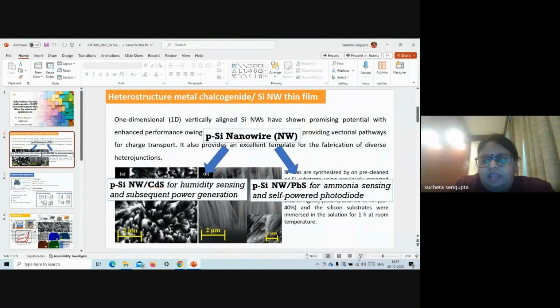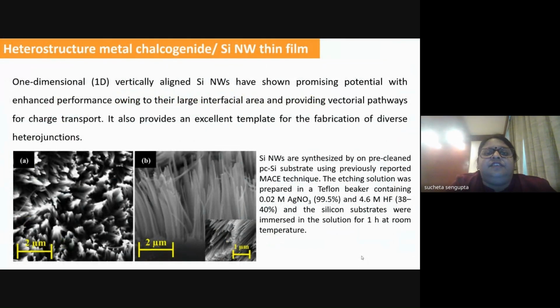So if we have silicon as the substrate, one-dimensional structures can be easily chemically etched over a large area very uniformly, and because of the one-dimensionality, they provide vectorial pathways for easier charge transport. And if you have heterostructures on that, then they have a larger interfacial area where these heterostructures can be formed. So in our group, we have synthesized silicon nanowires over a millimeter by millimeter size area, quite uniformly, by the MACE technique, metal assisted chemical etching, where it is etched with the help of AgNO3 and HF.